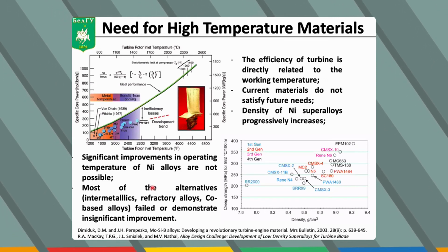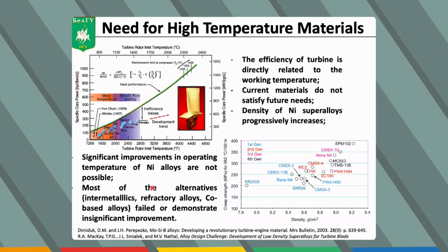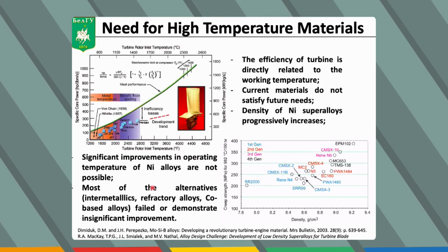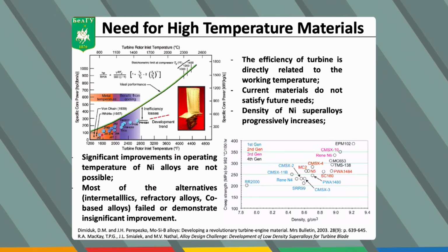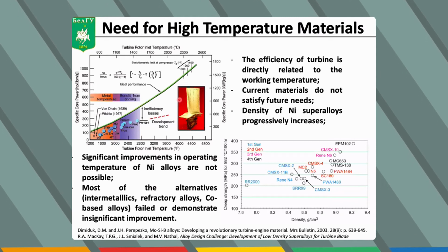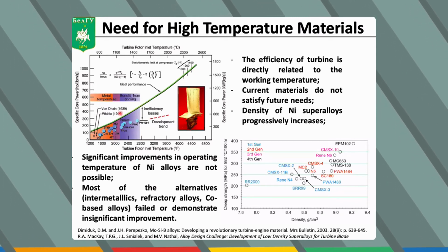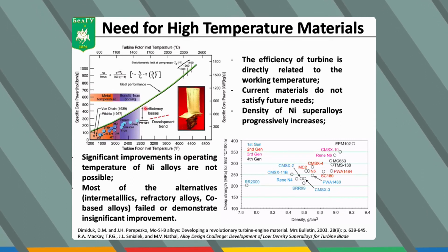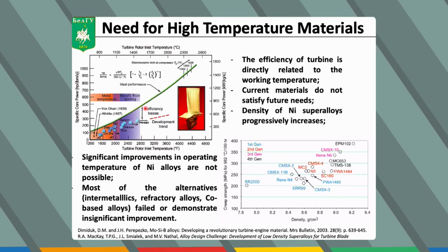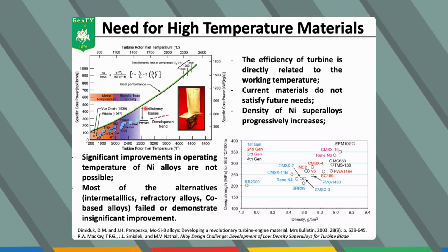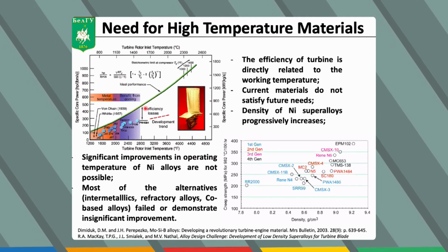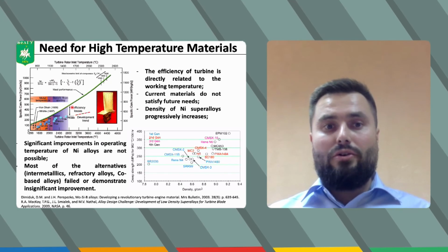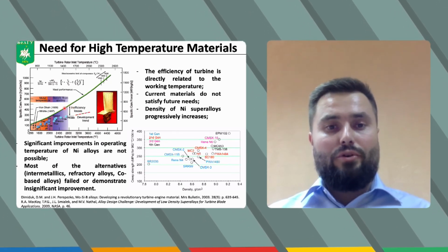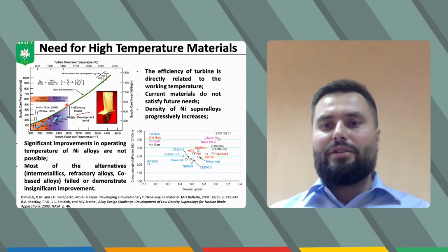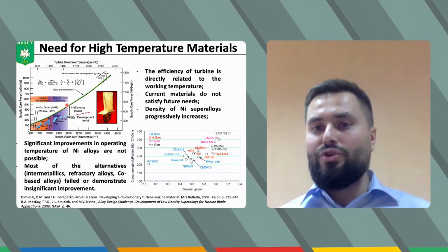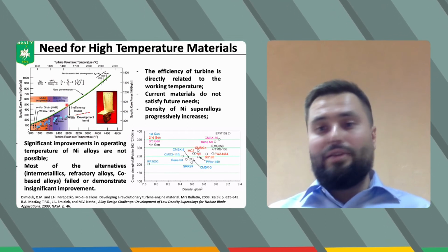And the answer is quite straightforward. We need to build new, more effective vehicles, machinery, including aircraft. And it's well known that the efficiency and the power of the turbine engine is directly proportional to its working temperature. And the aerospace industry for decades has used the so-called nickel-based superalloys for the hottest part of the turbines. But unfortunately, now these alloys are working at their limits. The working temperature of the engine approaches 90% of the melting temperature of these alloys. And unfortunately, we cannot push the melting temperature of these alloys any further.